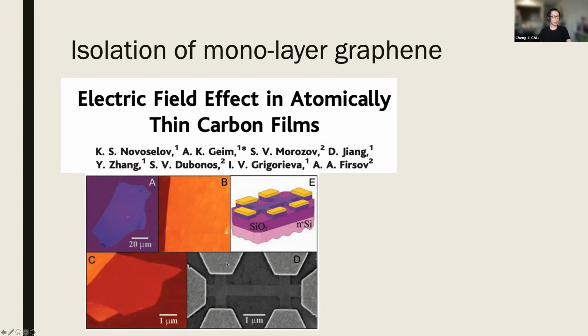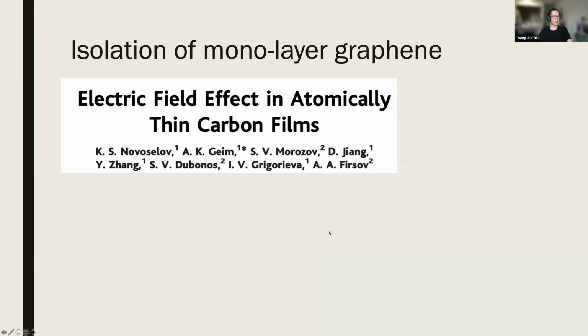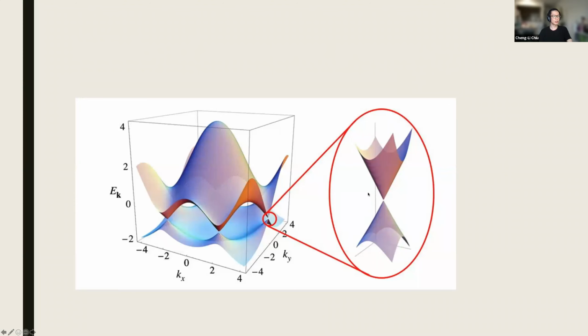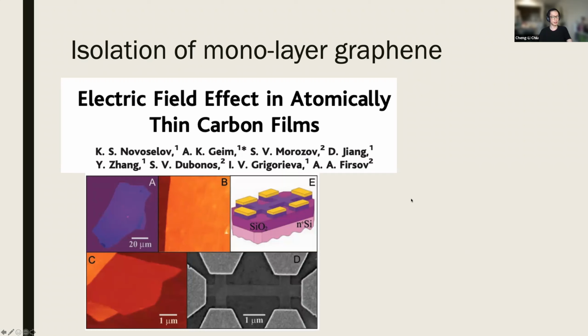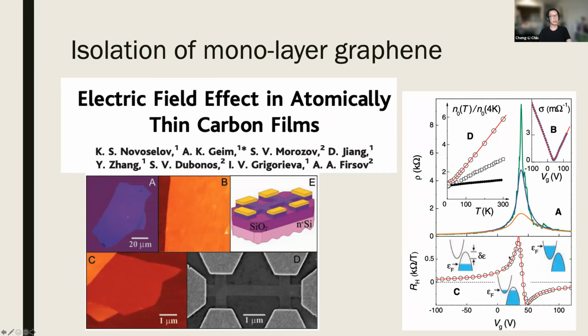And if you put it down on the silicon oxide, sometimes it will be dropped, and then you get a monolayer of graphene deposited on your silicon oxide wafer. Then you can fabricate it and make all kinds of devices. This is really a nice 2D material, because it only has one atomic layer. It doesn't have a finite thickness to affect our quantum Hall effect. And also you can gate it because you have a dielectric. If you apply some voltage on the material below, which is silicon, you can dope it, and then you can move your chemical potential from the Dirac cone to other locations, and you can change the electron behavior significantly.